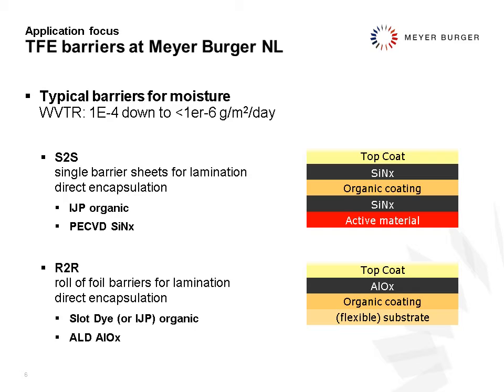So there is an active material that needs protection, and then a dyad of silicon nitride and organic coating, and silicon nitride on top coat to protect from the outside. For roll to roll, we can also offer a roll to roll solution, and there the target will be to realize a roll of foil barriers for the lamination. And direct encapsulation is a little bit more challenging because you have to have rolls of devices. So still possible, but